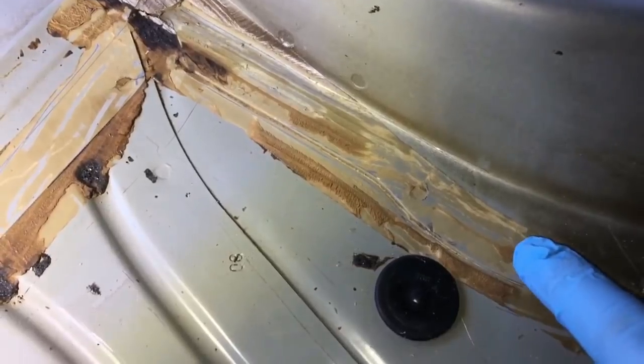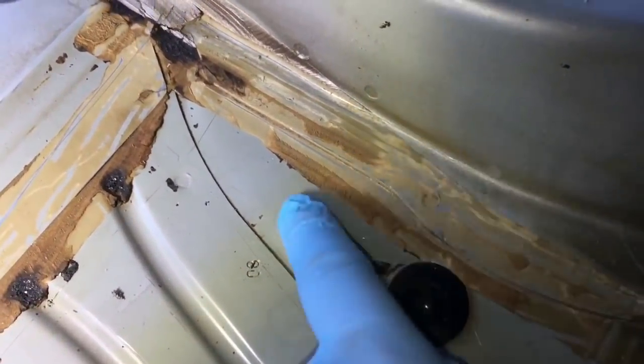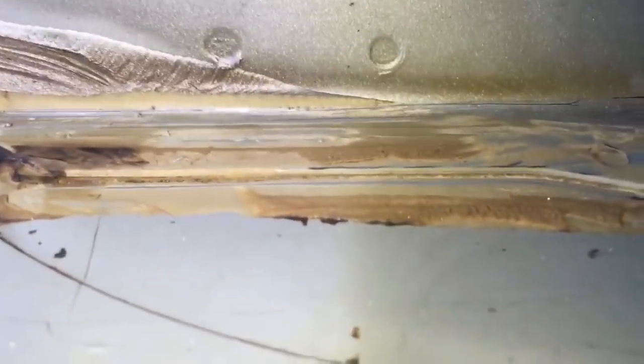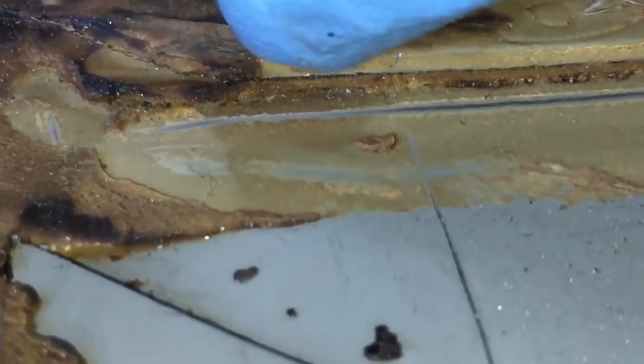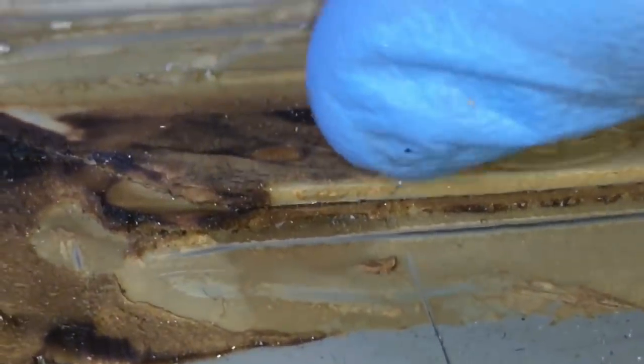This is the rear axle carrier panel, and this is the chassis leg flange. Spot weld, spot weld, spot weld, and it's held to this chassis leg. And if you keep an eye on the join over here where the sealer is sort of filled up the void, as you move slightly across to this corner join, you can see a gap opening up just here. There's like a black shadow under the flange. 1.2mm thick this is, the chassis leg flange, and it's very slightly started to drop, which is also in the same corner as that broken spot weld in the middle of the screen now.